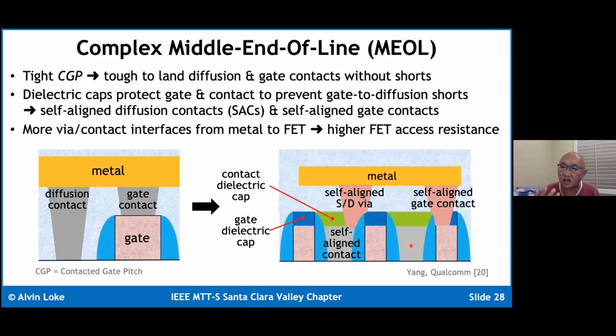So this is extremely complicated, as you can imagine. It's not uncommon to have what was one mask in 28 nanometers blow up to more than a dozen masks to build the middle end of line. And you can see that there are more and more interfaces because you've got more and more vias and metal and so forth. The net result is the access resistance to the transistor has just gotten that much worse.